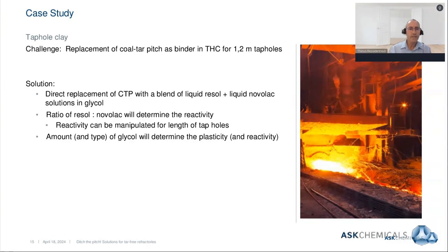Again, we first look at a case study. In this case, we chose a taphole clay of 1.2 meter length, replacing the coal tar pitch directly in a 1-to-1 ratio in terms of solids content by calculation. The solution we provided in this case was to use a blend of liquid resols and liquid novolacs in glycols. What I would recommend is that if you are a formulator of taphole clays, consider using these components separately to give yourself the ability to manipulate the reactivity of the final taphole clay.